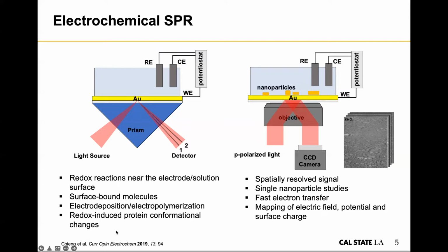Now, if you make a small change and move from a spectrometer to a microscope, you can get electrochemical reactions mirrored with the images. So we can get image sequences, and within the image sequences, we can look at different areas of the sample, look for individual particles, and extract information on those individual particles. This is actually the setup we have been using for our ongoing research.